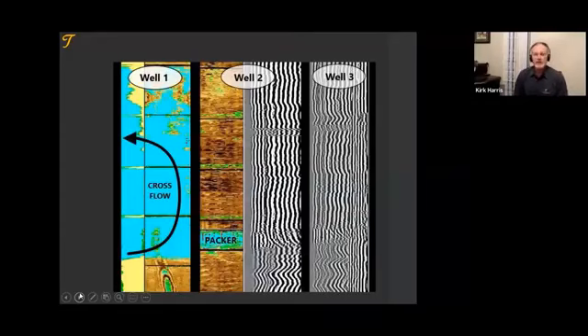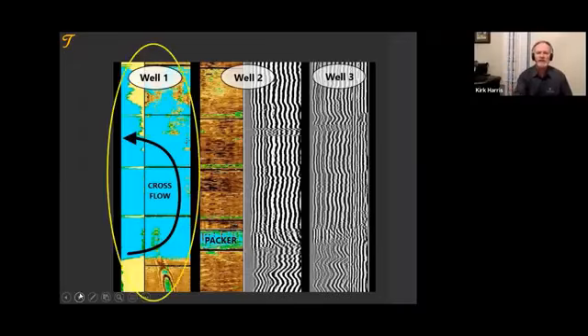Trust me, gel strength will not stop that cross flow. You need compressive strength or a mechanical barrier. This is a 200 psi over a short distance cross flow of CO2. If you start operating in the world of critical static gel strength, you will not solve this problem. We have to think of it in more practical terms of compressive strength or mechanical barriers, or some other thoughts. Compressibility is one way to stop gas flow.